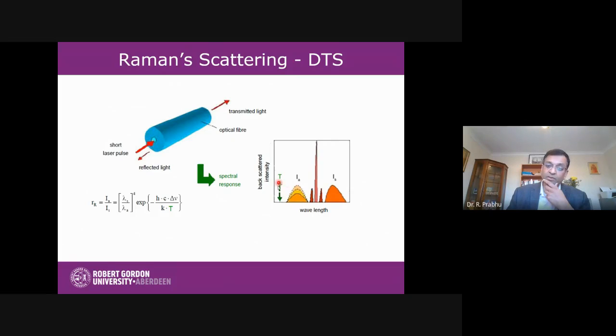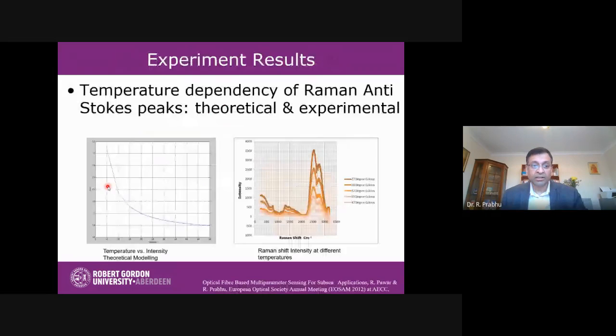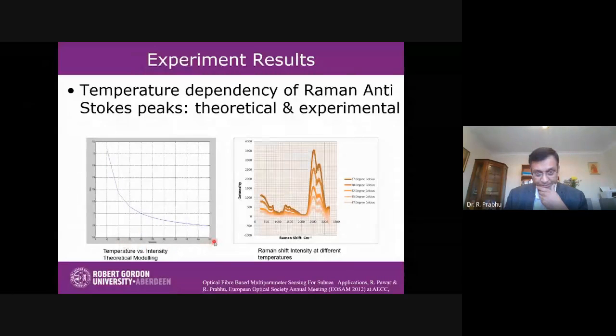And anti-Stokes is a function of temperature, or the amplitude of the anti-Stokes line is a function of temperature. That can be related to this equation, where the ratio of the anti-Stokes to Stokes line is an exponential function related to temperature. Temperature variation will result in a change in the reflected intensity. So you can see this is the exponential variation of the reflected intensity as a function of temperature. The reflected intensity of the Raman signal reduces as a function of temperature. This is the theoretical modeling.